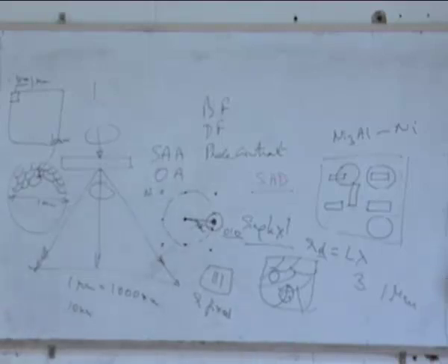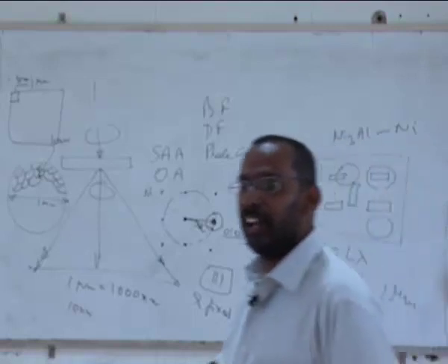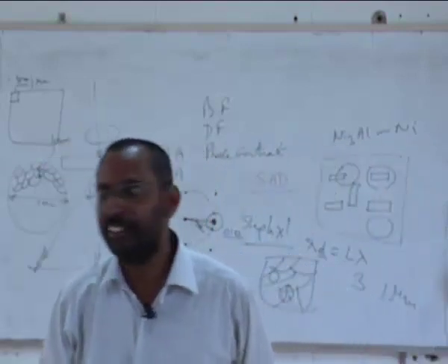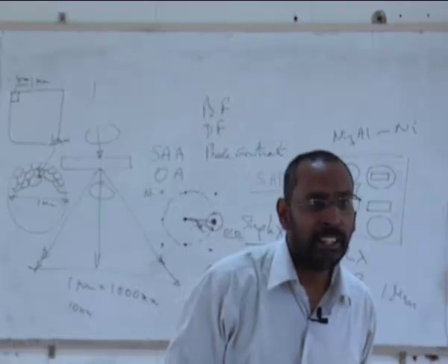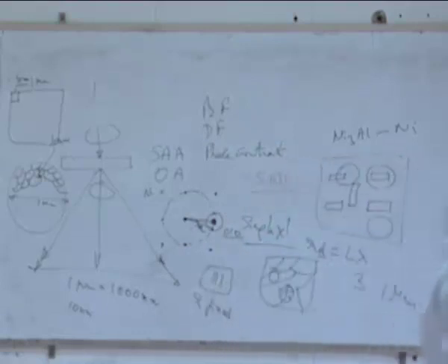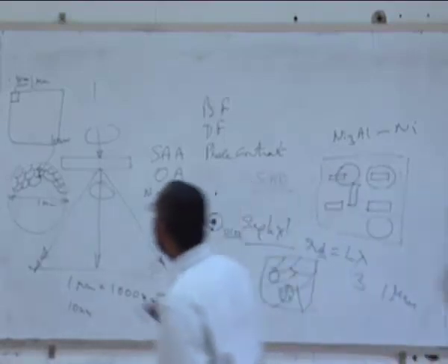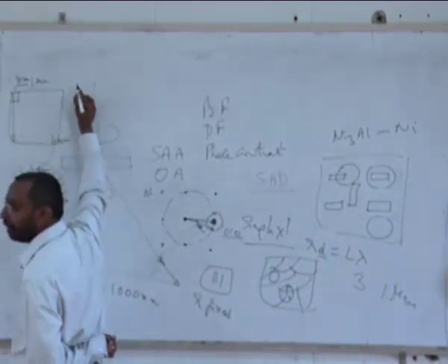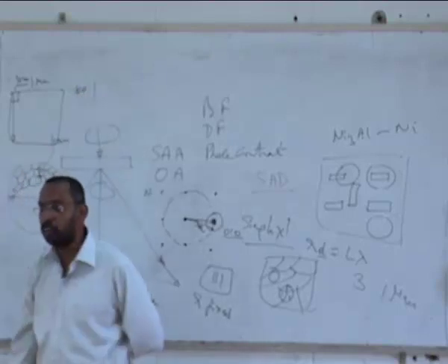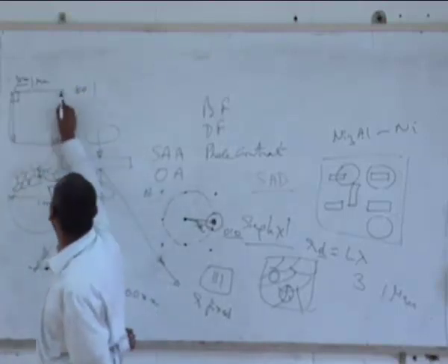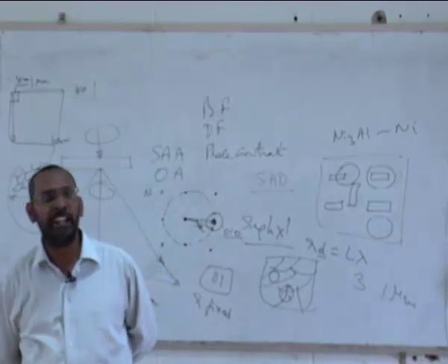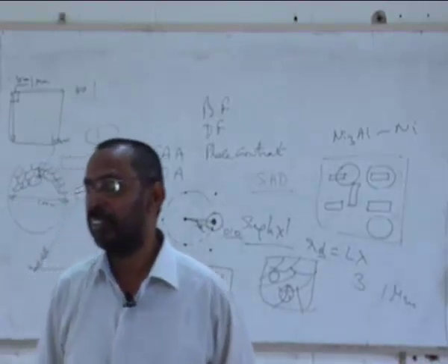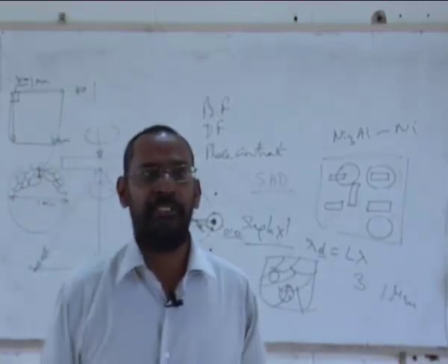This is much easier. I am taking a square and the grains are also square, let us say. It is 10 power 4, right? Because in one direction I will have 1 micron by 10 nanometer, that is 1000 by 10, about 100. And in another direction I will again have 100. It is 100 into 100. It is 10,000 grains.